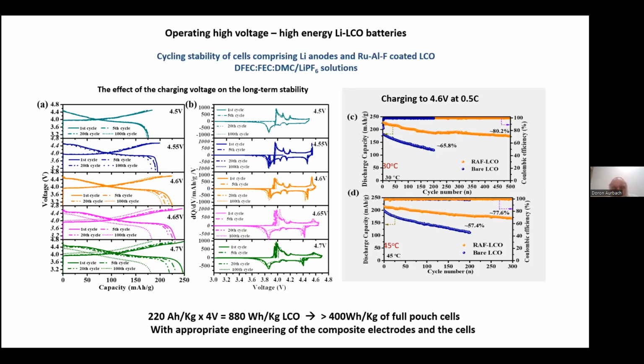Now the question is, by what number do we have to divide it in order to be realistic? And it appears that if we do good engineering, the number can be 2 point something, something between 2 and 3. But this means that we have a very good chance to reach a specific energy density of more than 400 watt hour per kilogram. And this is beautiful. This is very nice. I think here we can really reach the highest energy density, combining lithium metal and high voltage LCO, going up to 4.6 volts.